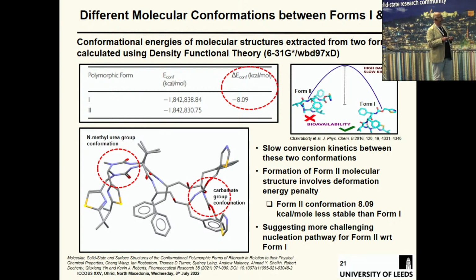And then when we look at the conformations, finding the conformational minimum for a molecule as big as that is no small task. I don't know what the most stable molecule is. That's been studied, but not described terribly well. But if you just calculate the single point energies of the two conformers, you realize that form 2 has a strain energy of around 8 kilocalories per mole. So to get it into form 2, the molecule has to distort away from where it ideally wants to be.